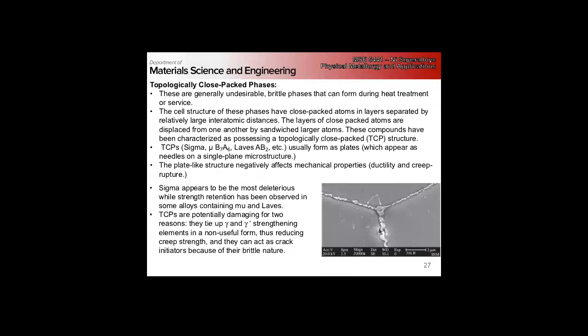Sigma is the worst. Precipitates out at grain boundaries. Sigma is particularly bad because it sucks up all of our strengthening elements to form, so it reduces strength, and then they're very brittle. Anytime you have a brittle, nearly interconnected phase at the grain boundary, you know that's going to be bad news, because now you've got a short circuit brittle path through your entire microstructure.